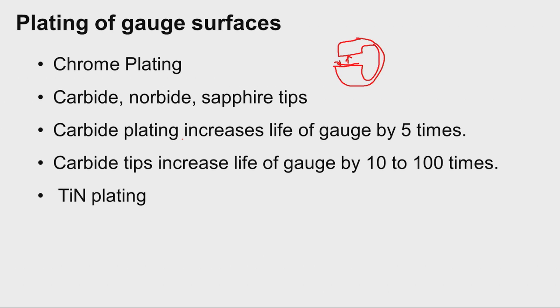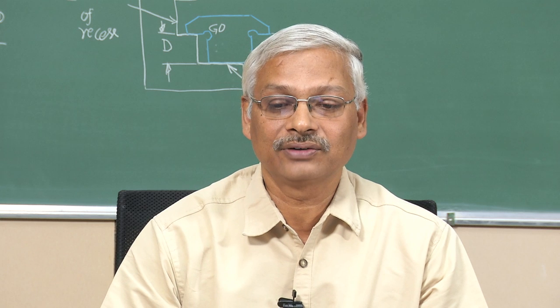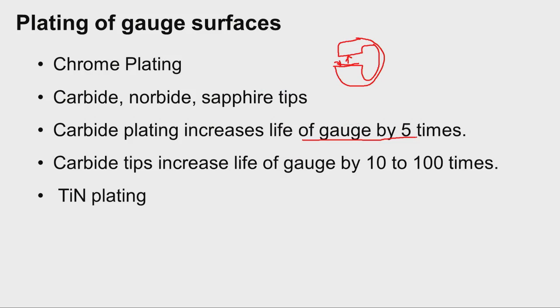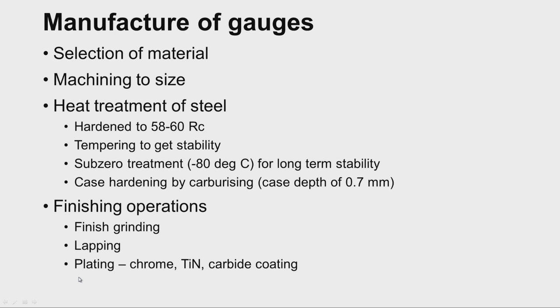And then carbide, the advantage of carbide plating is it increases the life of gauge by 5 times as compared to the only steel gauges. And carbide tips, if we are using a carbide tip, can be mounted on this, which will increase the service life of the gauge by 10 to 100 times. And TiN plating, titanium nitride plating, is also provided on the gauging surface, so that the service life enhances.